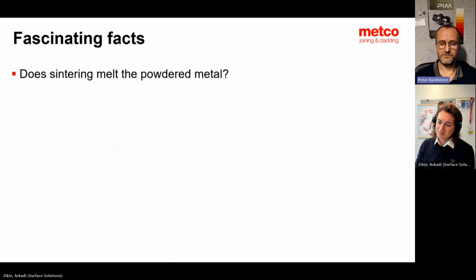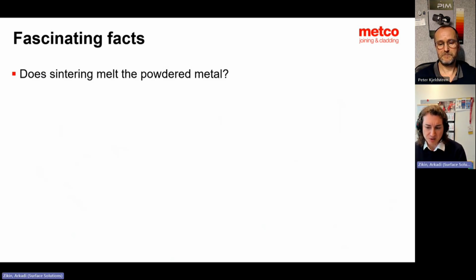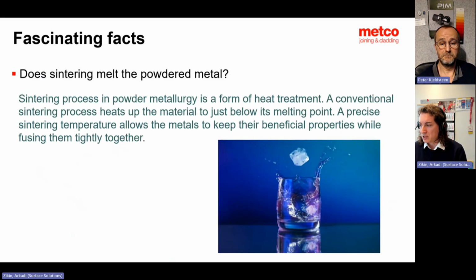Then shrinkage rate is a lot higher. You can have shrinkage rate up to 20%. That's correct. So it's pretty difficult to define the final shape. But by doing that, you can totally remove the porosities you typically have in standard sintering. That's true, but there you quite commonly move now to hot isostatic pressing nowadays.